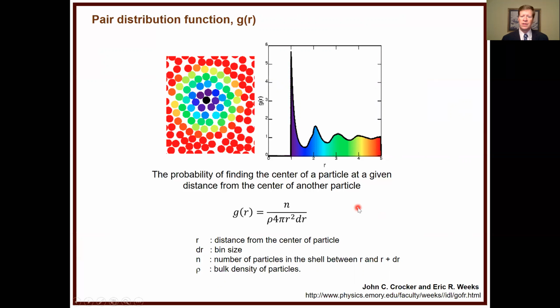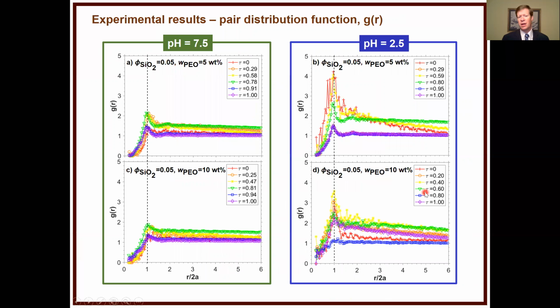And in this case, for these systems where it's random or gels, it doesn't actually tell you a lot of information. What we see is the first peak is actually relatively flat, and that first peak develops. Now, what may happen over time is that we have depletion interactions because we get so concentrated in polymer. And so to say that this is perfectly a liquid and perfectly a gel, it's hard to say, but we're going to have some evidence that I'm going to show you later on that makes you think that this is really more like a fluid, where the concentration every time, you can think of that as if I were to mix it at those concentrations and then randomize where everything is, what does that profile look like?